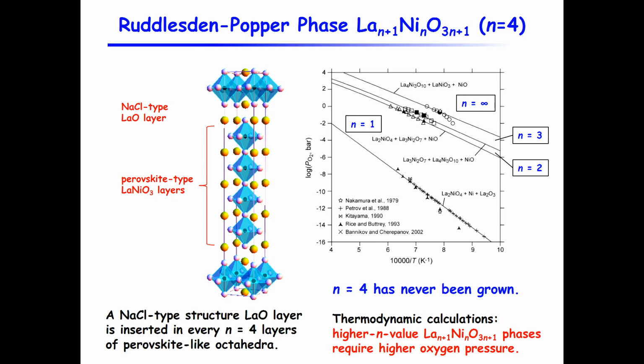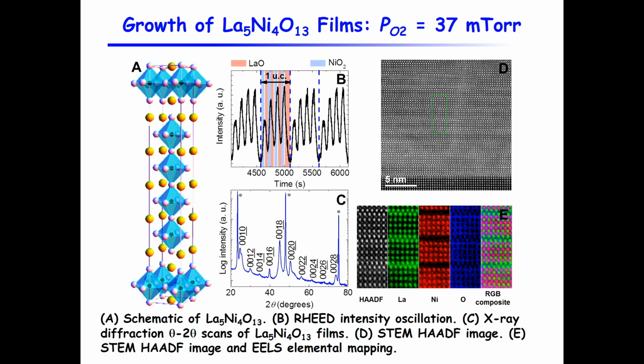But when people go to higher oxygen pressure, very often they cannot maintain the atomic layer by layer growth. So nobody has reported this earlier. But we use our technique. We have shown that we can grow this material. The deposition pressure we use is 37 millitorr, and it's high enough to allow the phase to be stabilized. Our technique allows us to go to this high oxygen pressure and still maintain the layer by layer